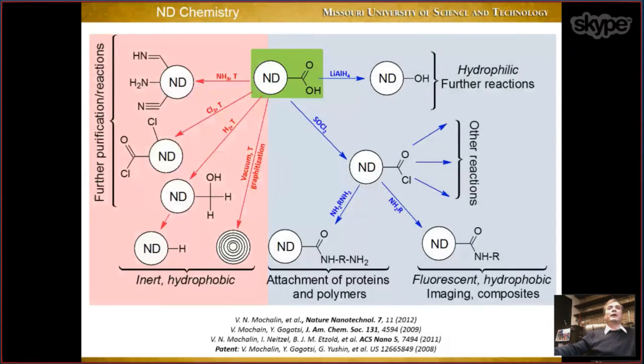Next step, after we have our material purified and deagglomerated, we functionalize the surface. After air oxidation, all the variety of different functional groups is converted into primarily just one type, the carboxylic group. So we have nanodiamond terminated with carboxylic groups. And then you can pretty much open your organic chemistry book, go to the chapter on chemistry of carboxylic groups, and try different reactions typical for carboxylic groups to functionalize nanodiamond. I just grouped these reactions here in this diagram very schematically.